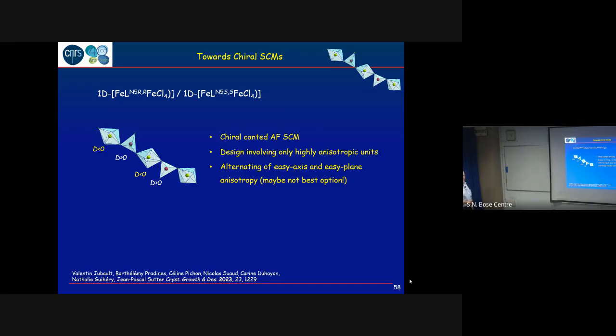Very small. So the drawback of all this work with iron is that we are not able to get large crystals, because the energy of the bonds with iron is large, and this limits the possibility. To get large crystals, you have to have an equilibrium between solid and liquid, and this is not the case here. So we have a very fast crystallization, and the result is a few hundreds of microns. So crystallography, EPR, things like that could be enough. But for making a sample for magnetometry, it's too small for the setup.